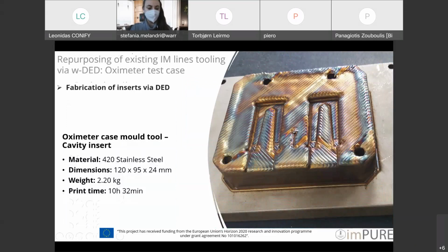As you can see here, the oximeter case mold was produced from 420 stainless steel. It weighs approximately 2 kilos, and it was completed in 10 hours and 30 minutes, more or less. We had a good surface finish, and we were really happy and satisfied with the end result. Next slide, please.